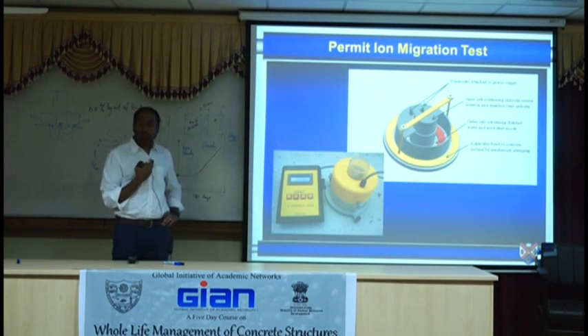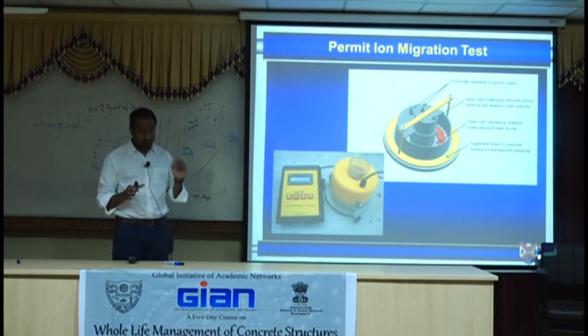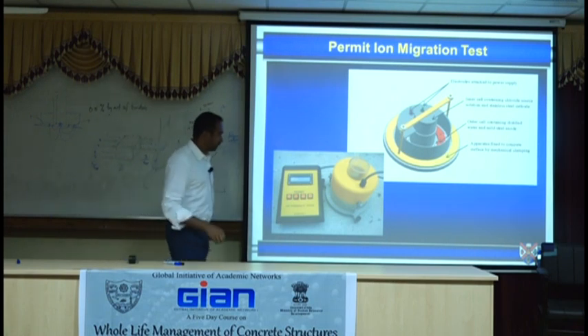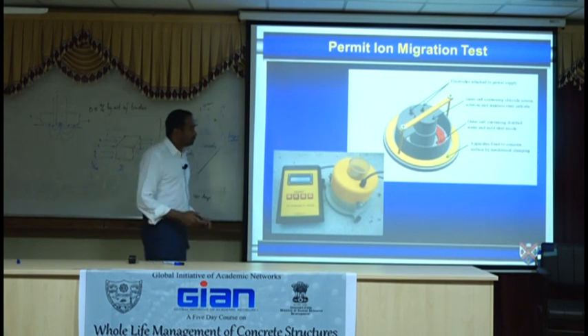Anybody using the test, I would suggest them to take a cube or take a slab, test it, break the slab, look at the chloride concentration in the slab by spraying silver nitrate. It gives you a feel of how far the chlorides go, what other results you get. Okay.